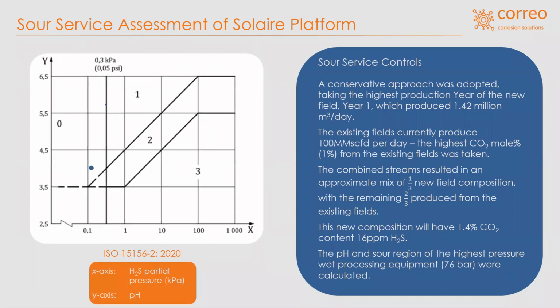There we go, the blue dot. But we took the extreme of this from the wet processing equipment at 76 bar to give us the highest input. So the whole system is not sour as far as we can make. The inputs into the first stage gas separator is dry gas, so there's no need to consider this kind of corrosion in this situation. And similarly, after the glycol contactor, there's no oil, H2S in the oil. So again, nothing to be concerned about.